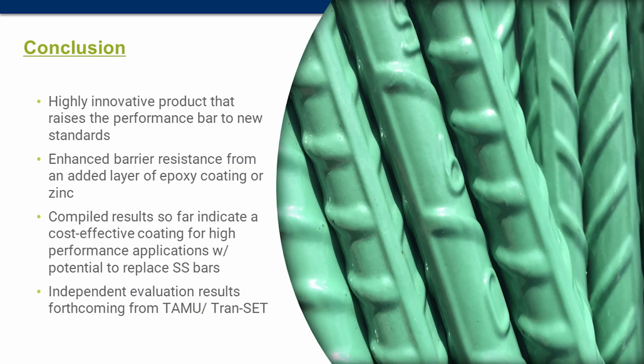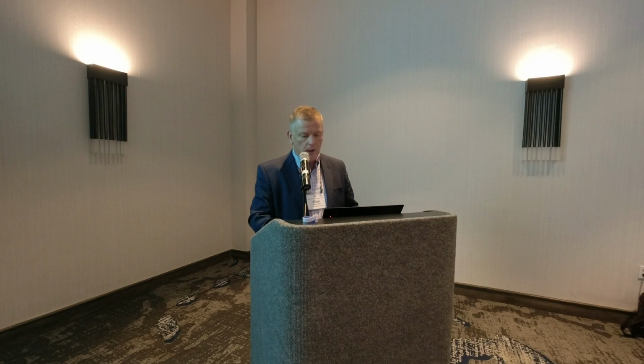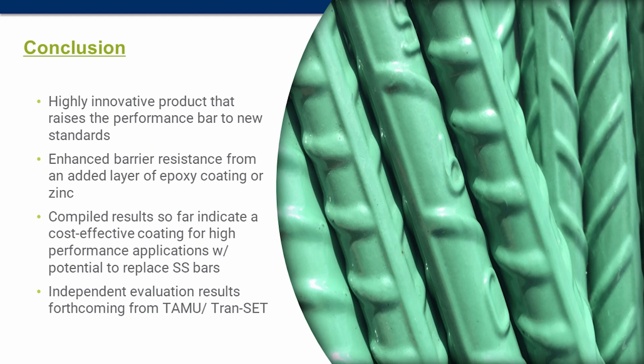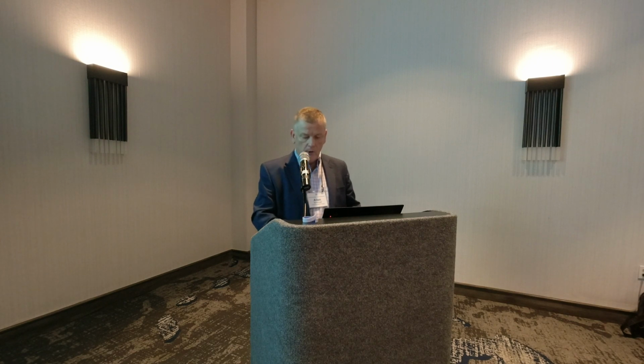And in conclusion, it's not only a highly innovative way to raise performance, but it's a more durable measure. Again, I mentioned redundancy, but that's really the key part here, whether you're coating with an epoxy or with a zinc coating. And then there's a lot of compiled results that indicate that this is a cost-effective way. It's 35 to 50% less than stainless steel to potentially replace stainless steel for a long-term replacement. And then I mentioned that at the Center for Infrastructure Research at Texas A&M University, there's a research study in progress that's looking at the dual coat technology.